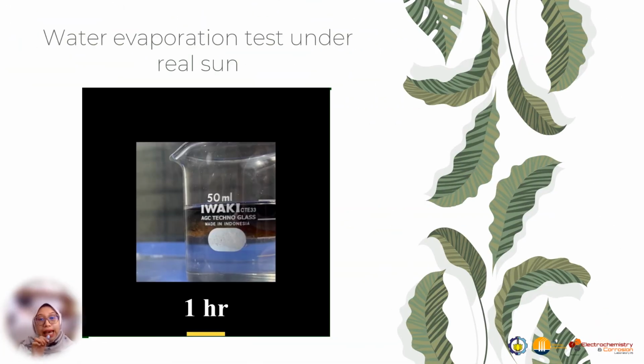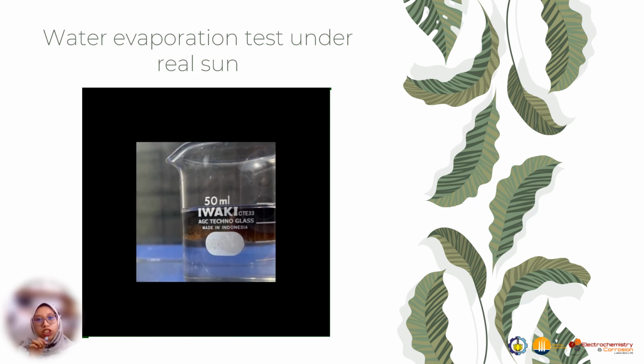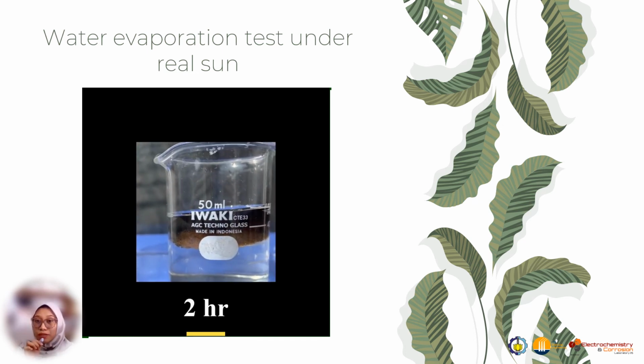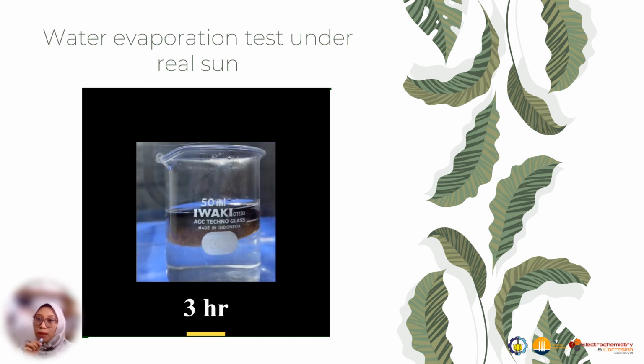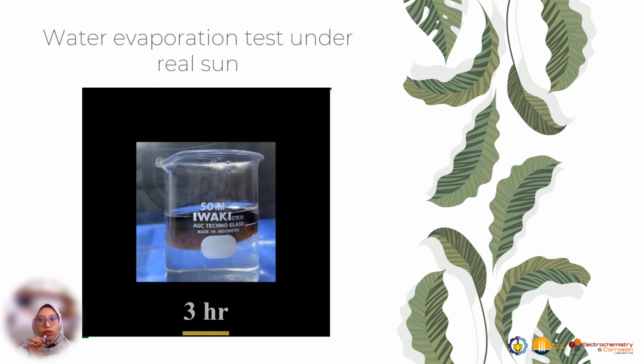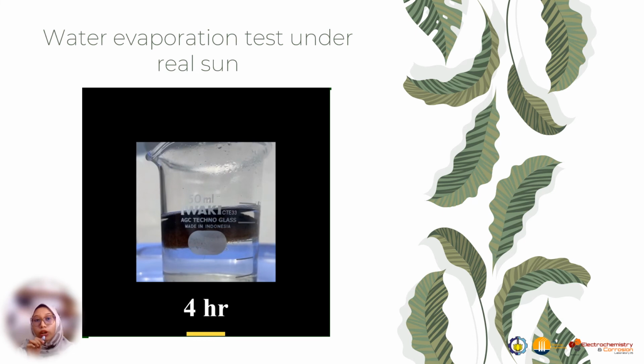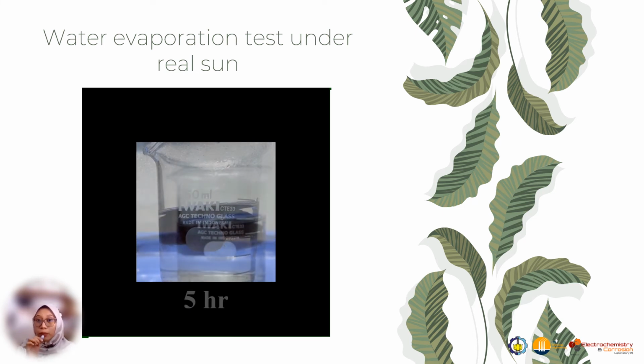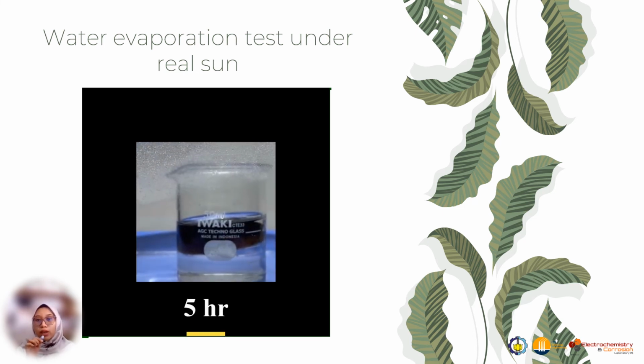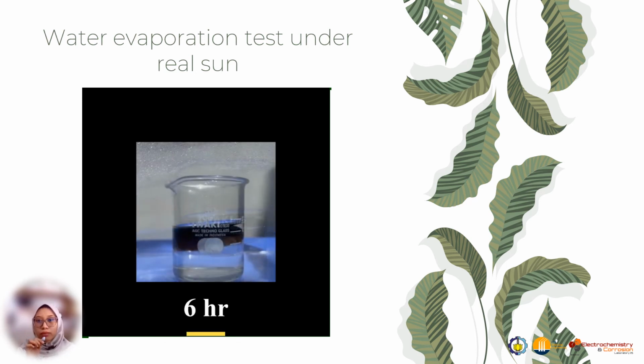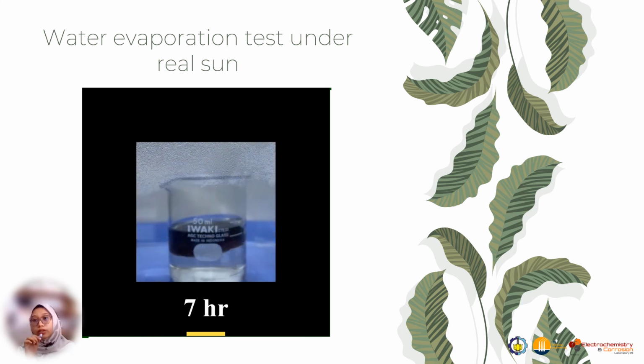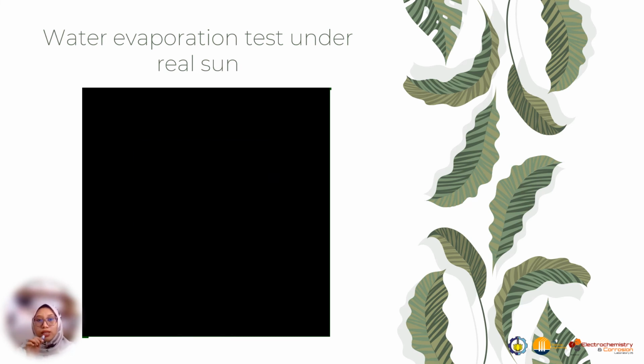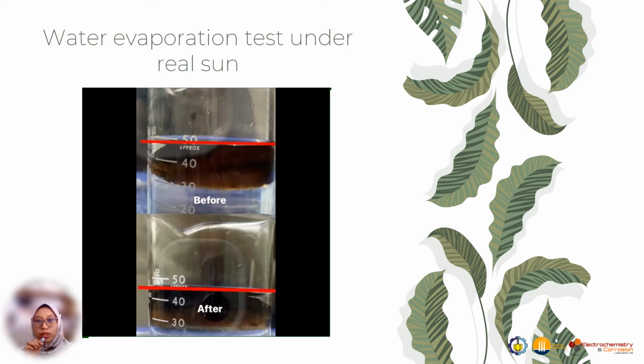To check its ability, we also did an experiment of water evaporation test under real sun from 7 a.m. until 3 p.m. It is clear the cellulose aerogel could evaporate the water in the beaker. The condensed vapor was taken to the acrylic housing, then trapped at the bottom of the acrylic housing. The last picture showed the water level decrease after the test, shown by the red line.